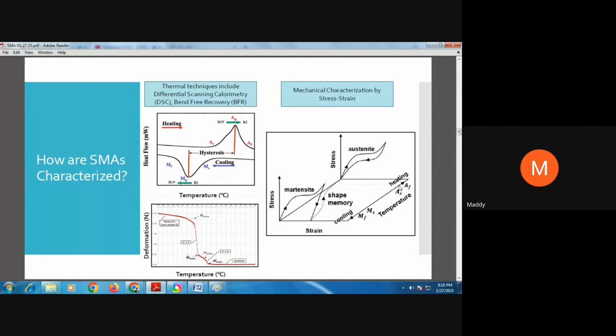The first chart is a schematic of the DSC. You have the heat flow on the y-axis and the temperature on the x-axis. And through this, when you heat and cool, you predominantly characterize three different temperatures: the start, the peak, and the finish of the forward transformation from austenite to martensite, which occurs on cooling, highlighted by the blue arrow. And then on heating is the reverse transformation, where again you quantify the austenitic start, peak, and finish temperature. DSC is typically used at the ingot level, or when you want to determine the composition of the material. We'll talk a little bit more about it in the melting slide, but DSC is used at the extreme upstream of the material manufacture.